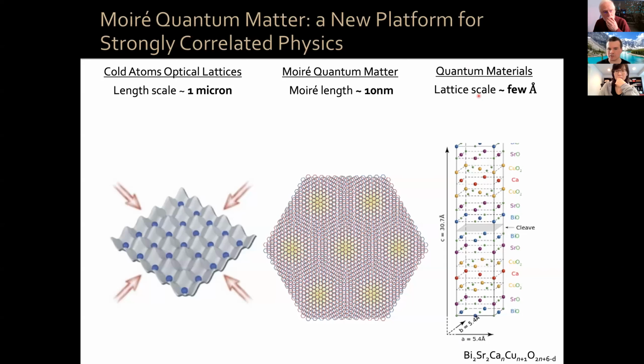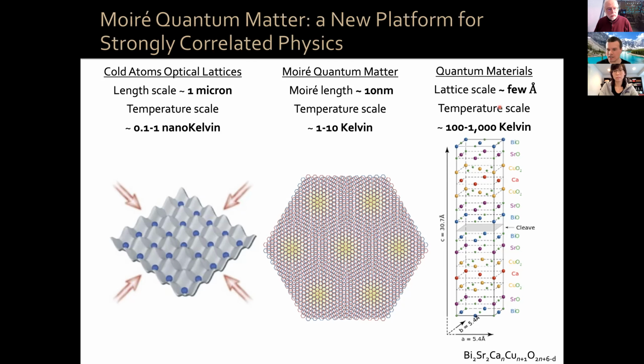About a couple of orders of magnitude, from either of these two platforms. Now, associated with these length scales are energy scales. So in quantum materials, typical energy scales are of the order of 100 or 1,000 Kelvin. In cold atoms, we're at 0.1 to 1 nanokelvin. In Moiré quantum matter, because we're at intermediate length scales, we're also at intermediate energy scales, 1 to 10 Kelvin, 1 to 100 Kelvin.